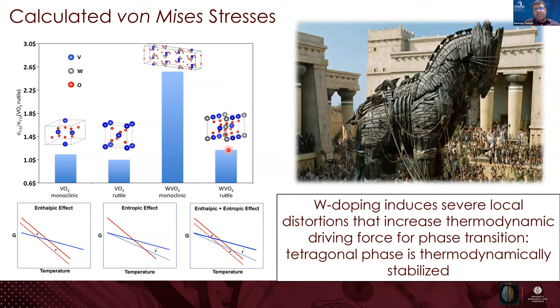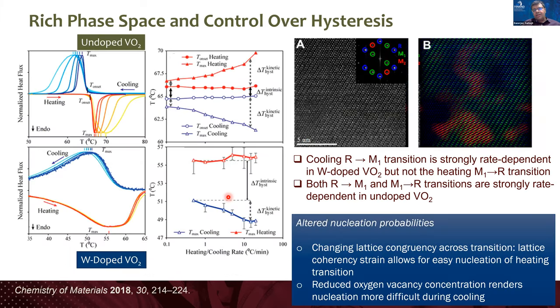And also immediately around the tungsten atom, we've done a lot of local probe measurements using methods such as XAFS. And you see an increase in local symmetry that looks a lot like this tetragonal rutile phase. So the tungsten atoms act as a Trojan horse, really, to induce this transformation.